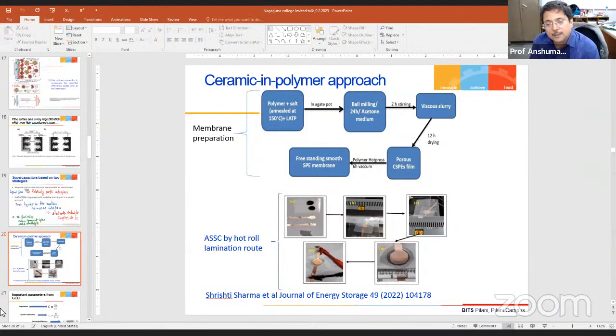So what we do is that here we also develop activated carbon. We coat the activated carbon on graphite using a simple Dr. Blade technique. And when the graphite is coated with activated carbon, simple job, you put your polymer film in between. This technique we developed does a hot roll lamination. So when you do lamination, then instantly the lamination layers go above the melting point, and then they are cooled also. When the material goes a little above the melting point, the interface is established smoothly.